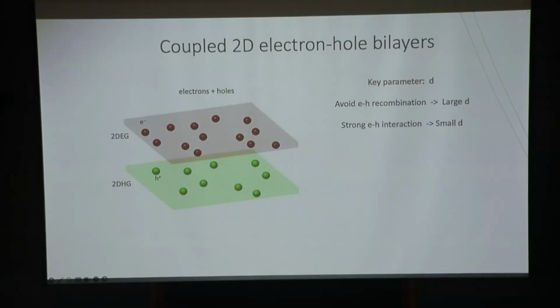And that led to this idea of electron-hole bilayers. So the idea is, not having electron and hole too close to each other. You put electrons in one layer and holes in another layer, and use a very large tunneling barrier to prevent the electron and hole from recombining. In this case, this electron and hole will have attractive interaction, and they live very long, and we can explore their ground state property.